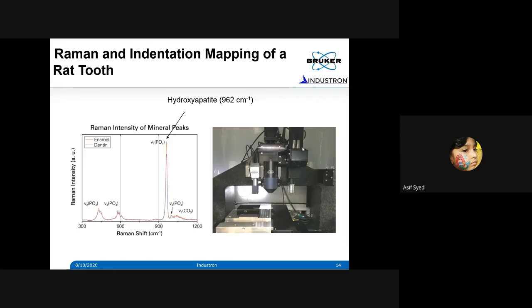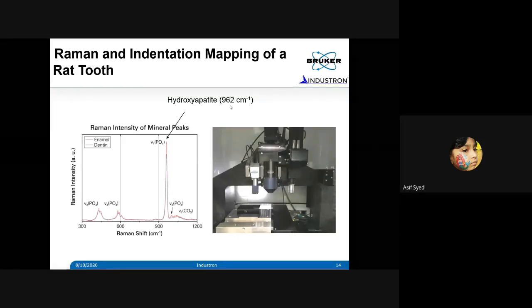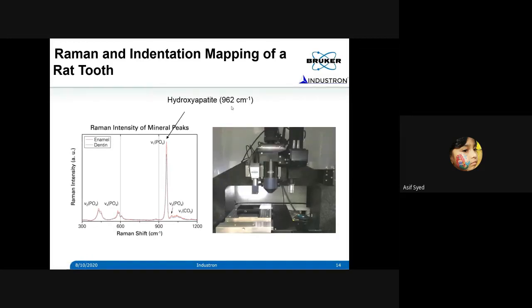For example, if you want to understand what type of mineral is there, you need to understand the chemistry of it. So Raman is one way of understanding the chemistry that you can attach with this kind of instrument on top of what you're trying to do with respect to indentation or scanning probe microscopy. We can add additional instrumentation like Raman microscopy to understand the chemistry on the surface. So in this case, you can see the hydroxyapatite peak at a wavenumber of 962, right? If you can watch that, and then you can measure the intensity of that peak at different locations, you know how much of that mineral is there on that particular site. So now you have a handle on the chemistry, you know what the content of that mineral is. So can we map that?